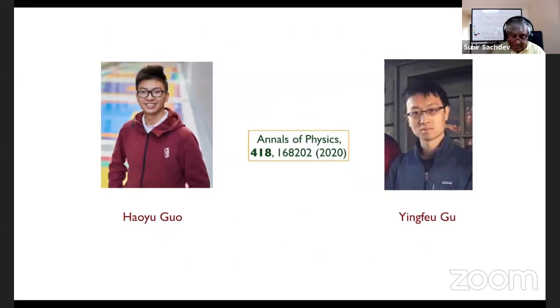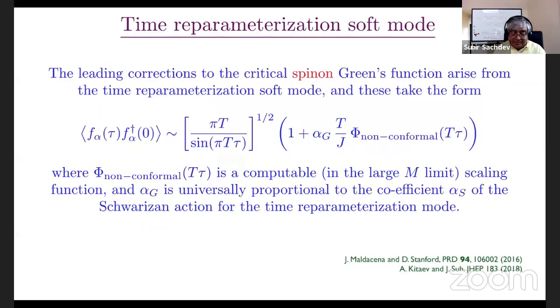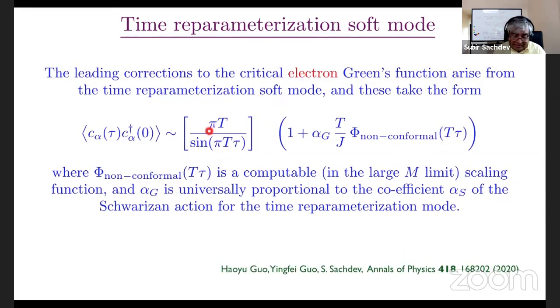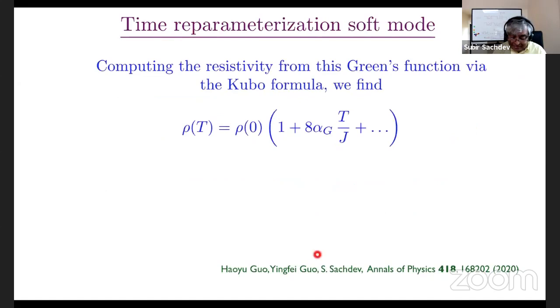Okay, so this is work done by Haoyu Guo and Yingfei Gu. So I already showed you this before. If you looked at the spinon operator, it had this 1/2 exponent with some non-conformal corrections, which went linearly with temperature or frequency. Now, if you look at the electron operator, you lose the 1/2, it becomes 1, and this part gives you the residual resistivity. For the leading correction, and this is, again, a very general argument coming from this time reparametrization symmetry, it has to be a linear function of temperature. And this is something you can compute. So from this, you can compute the resistivity, and this is what's in this paper. And at least from the time reparametrization mode, you then get a correction that's linear in temperature.